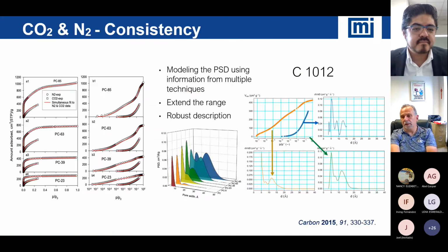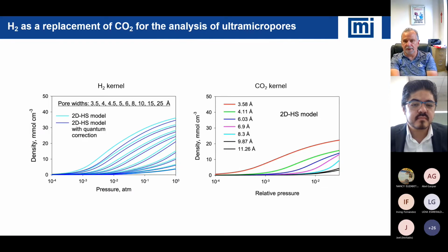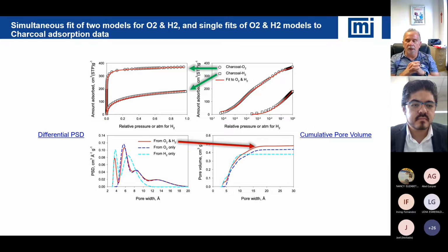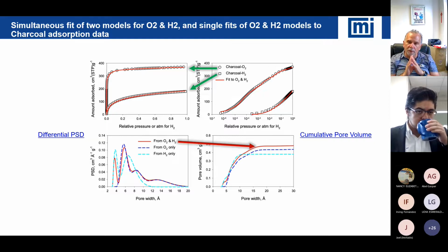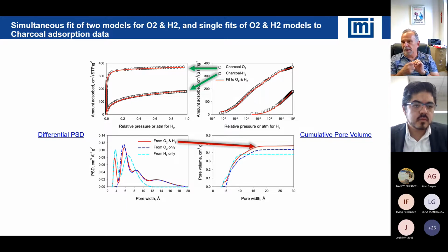So reporting the fit. Reporting the fit is really critical, and particularly with gases like argon, nitrogen, oxygen, wherever the fluid where you can actually get to complete saturation and condensation tends to be really critical. And the place where it's critical is when you report the fit, and the best way would be, as you're looking at this slide in the upper right corner, you don't want to see any unusual wiggles in the fit. So you really want to see a good representation of the original isotherm.